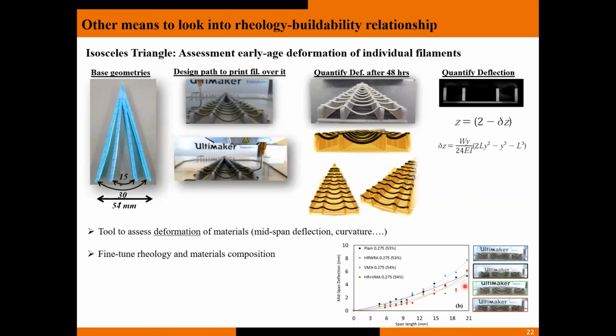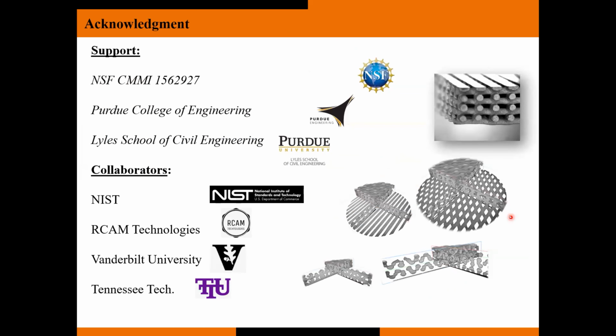We also looked at an isosceles triangle as a means to come up with a quantitative way to assess the deflection of single filaments. The test helped us look at the ability to span over varied lengths and help characterize the amount of deformation in a neat cement paste as opposed to a cement paste with high range water reducing admixtures and viscosity modifying admixtures, which were all quantified using micro CT.